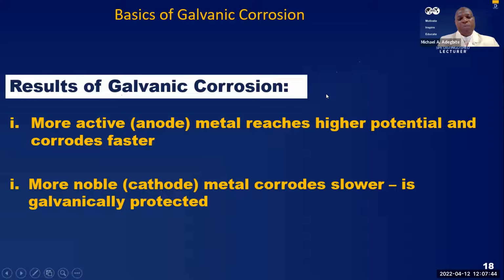So a more active metal, that's the anode, reaches higher potential and corrodes faster. And the more noble one is the cathode, and corrodes slower or at a lesser rate, is being protected, galvanically protected by the anode. So the cathode enjoys a measure of protection, and that is what happens when we have preferential weld corrosion. So whenever we have preferential corrosion, it means that the parent metal is enjoying considerable protection while the weld metal and or the heat affected zone goes into solution.